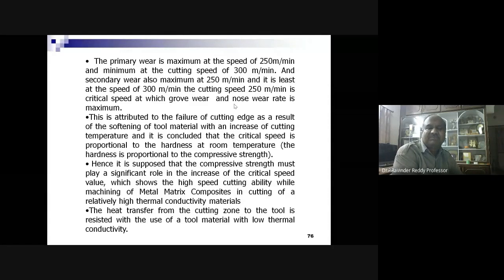The cutting speed 250 meter per minute is the critical speed at which the groove wear and nose wear rate is maximum. This is attributed to the failure of the cutting edge as a result of softening of tool material with an increase of cutting temperature, and it is concluded that the critical speed is proportional to the hardness at room temperature. The hardness is proportional to the compressive strength, as you know. Hence, it is supposed that the compressive strength must play a significant role in the increase of the critical speed, which shows the high speed cutting ability